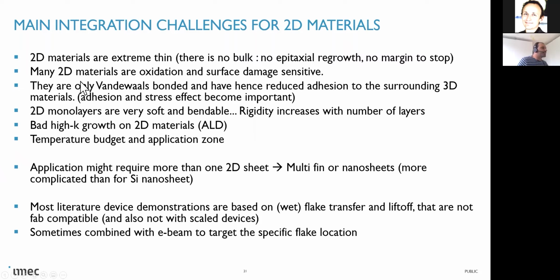So the other thing is that these materials, if you expose them to the air, or you're depositing in an oxidizing ambient, are very prone to oxidation and surface damage sensitive. So adhesion will also be a very big challenge, and we are suffering from that problem all the time. A single layer 2D is very soft and bendable, and this will also be a very big challenge,